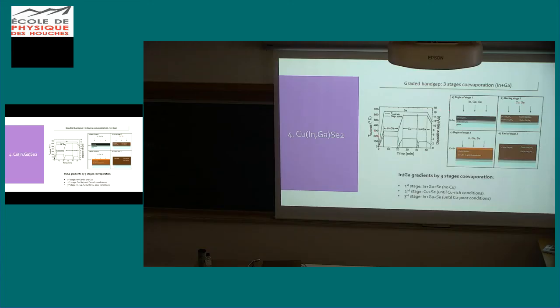To achieve a gallium graded band gap, the three-stage co-evaporation process is the best one, because during the co-evaporation of copper, indium, gallium, diselenide, you split your process in three stages. In the first stage, you introduce only indium and gallium. In the second stage, you start to introduce copper until copper-rich conditions. Then you stop copper and once again introduce indium and gallium until copper-poor conditions. And normally you keep gallium-rich at the back, gallium-poor in the middle, and gallium-rich once again at the top.